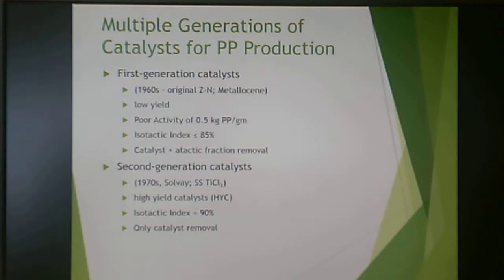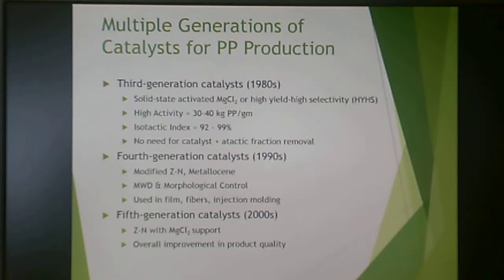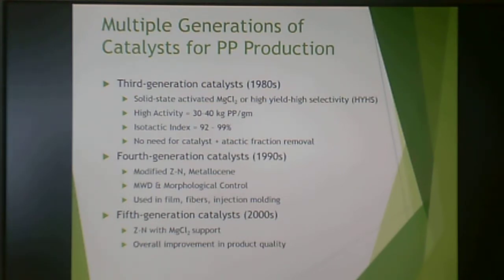With the first generation, you also had to remove the catalyst and the atactic fraction. With the second generation, you got higher yield, higher isotactic index, and you only had to worry about removing the catalyst. With the third generation, you got an even greater isotactic index and no need for catalyst removal.